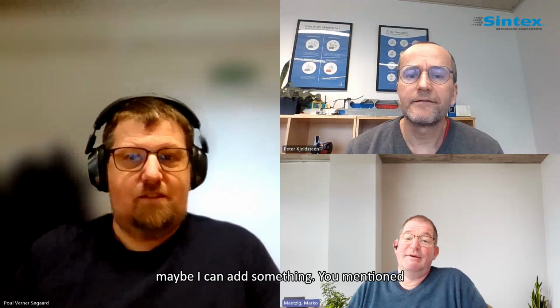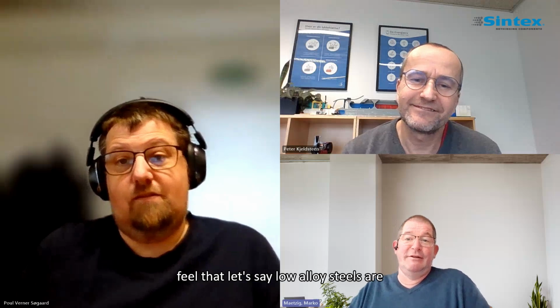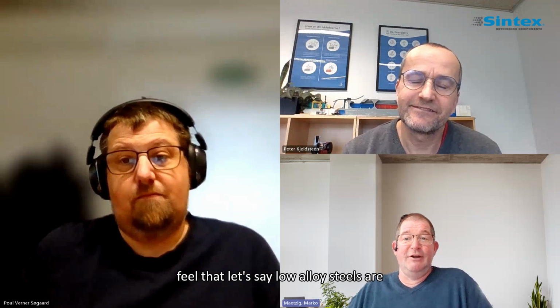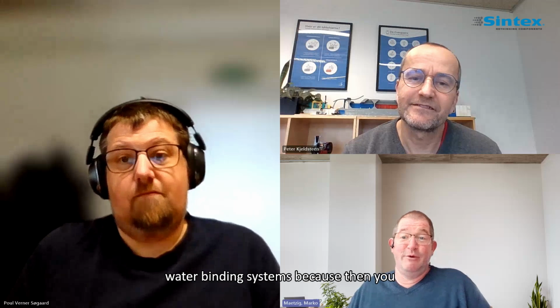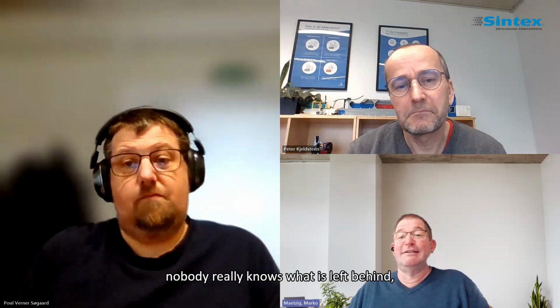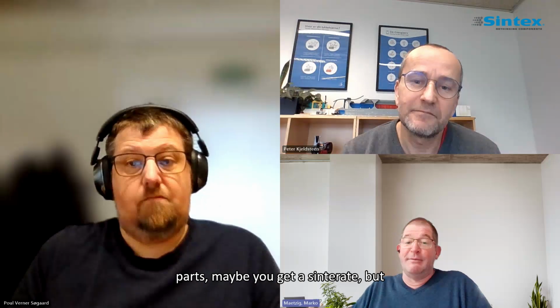Maybe I can add something. You mentioned that copper is not very good with a catalytic process. On the other hand, I feel that low alloy steels are not working very well with water debinding systems, because then you need a corrosion inhibitor, and nobody really knows what is left behind once you dry the parts. Maybe you get a sinterate, but maybe you don't. So there are pros and cons in all directions.